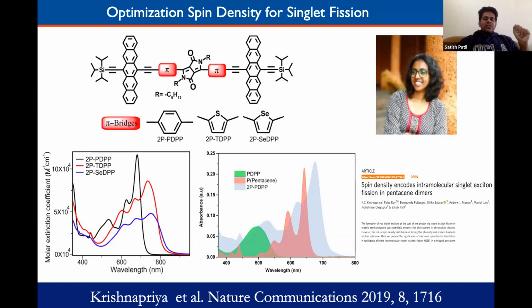So this is the work which she published last year, where she looks at the optical properties. You see that in a simple absorption spectra of a dye, there is indeed a difference in electronic coupling. Here is a phenyl one, which has a very high oscillator strength and very high extinction coefficient, but it is blue shifted. When you put thiophene and selenophene, it's red shifted.